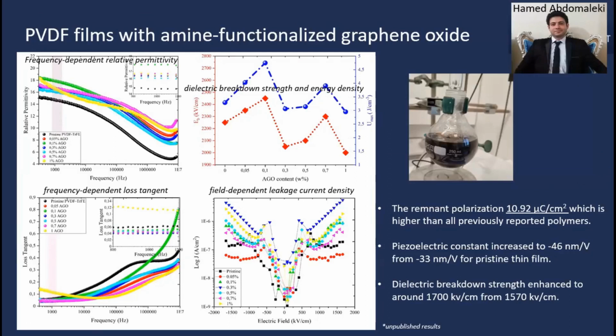And what we found was that because of this 2D graphene, it's a two-dimensional structure in a 3D matrix. Basically, it forms microcapacitors within the material itself. And because of the interaction of AGO with PVDF, we were able to get really great, outstanding piezoelectric properties from this PVDF. So we increased the properties by a tremendous amount, as you can see. For any range of frequencies, you get really high permittivity values. Even your breakdown strength increases quite a lot for certain combinations.